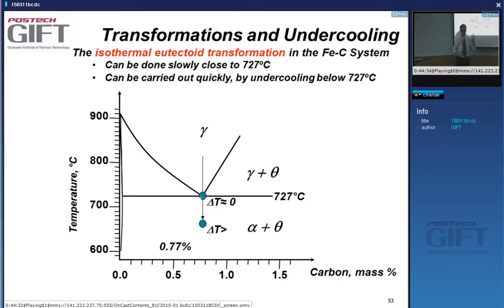The phase diagram tells me it's homogeneously austenite, yes? And then I have another furnace next to it. That furnace can be, for instance, 650. So I take my sample and I put it in that furnace, yeah? What I'm doing is an isothermal transformation, yes? So at 650, the austenite is not stable anymore, and I will get a transformation, a formation of pearlite now, yes,